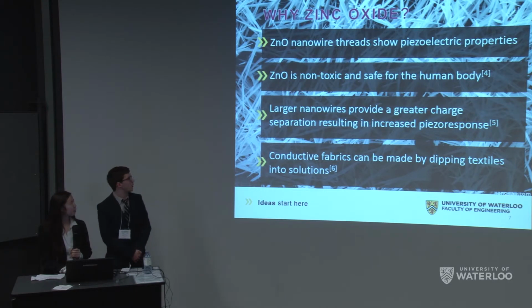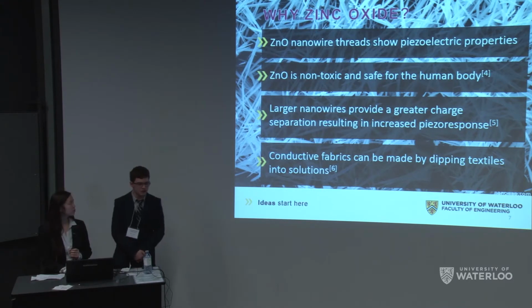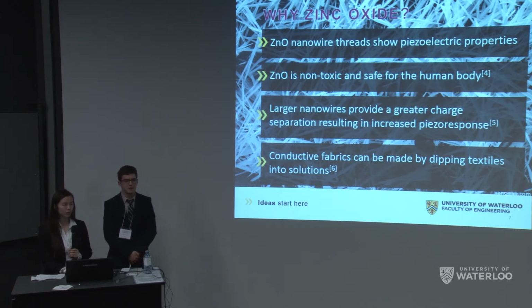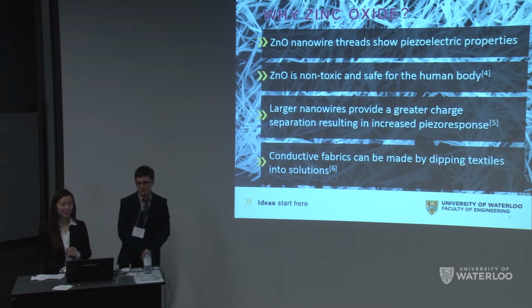So let's take a look. Oh, and also we chose to use larger nanowires. Initially we tried to use smaller ones, but based on our testing, we switched to large. So we used nanowires that had 4 to 5 micrometer length and 300 nanometer diameter. This was because they have increased conductivity as well as an increased piezoelectric response due to the greater built-in potential.